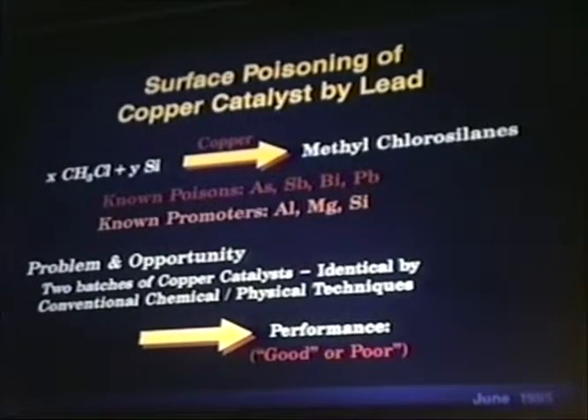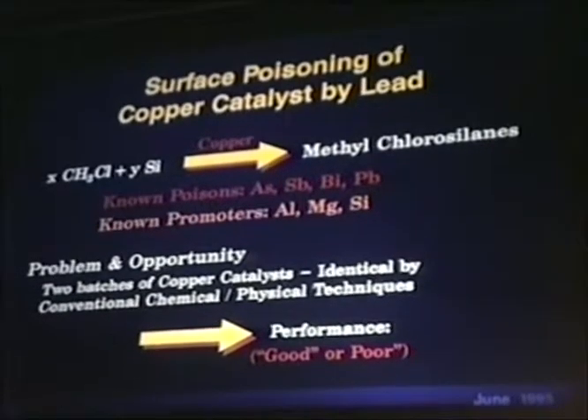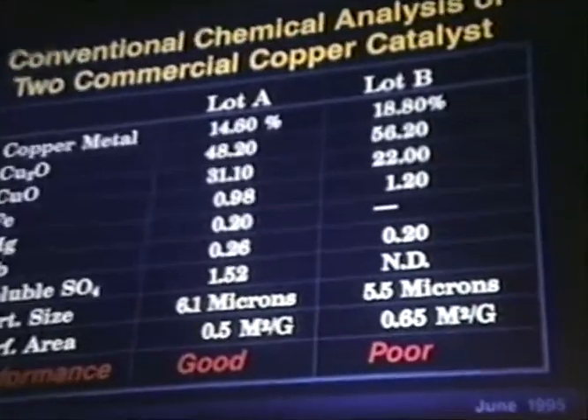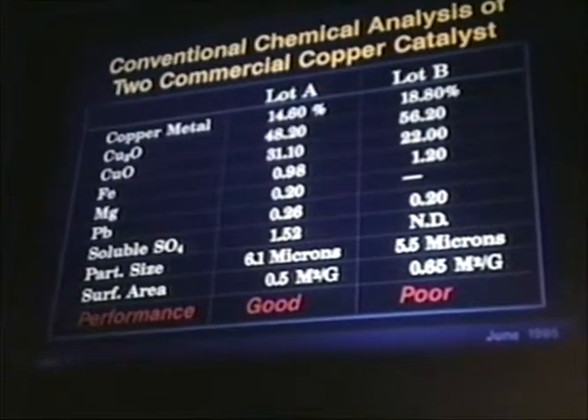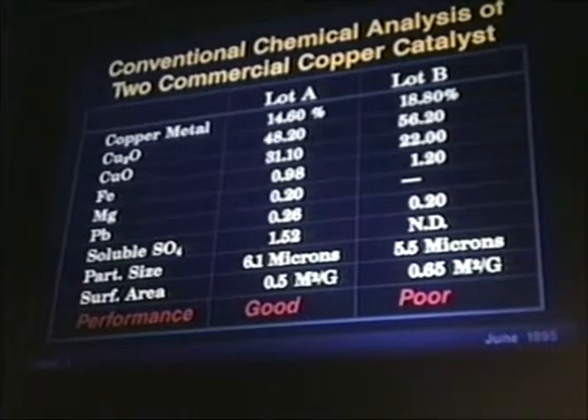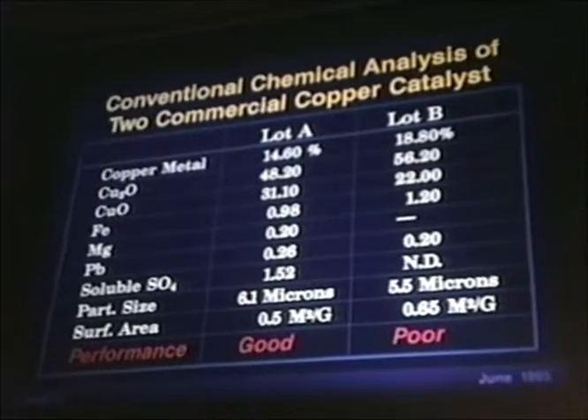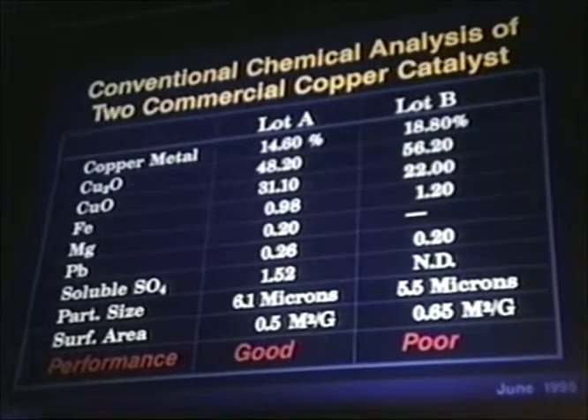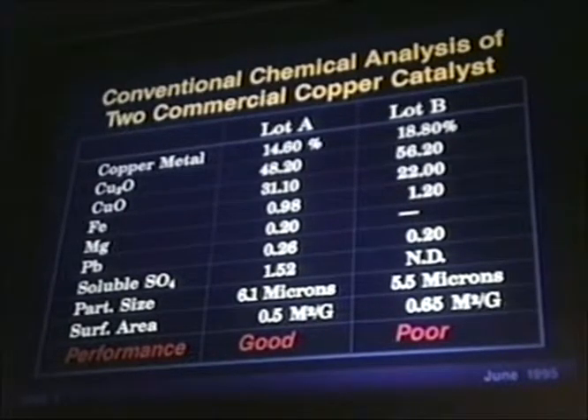It's a commercial process, and we have had in the early days of surface science a real problem, and that is some batches of catalysts will be made and we could not distinguish the performance of the good and the poor catalyst systems. But it was also an opportunity. Doing the conventional analysis, which is covered here, you can look at all the detailed analysis of both the oxidation state, cuprous, cuprate, and all the other impurities, and the soluble sulfate particle size, if anything, was in the other direction, yet the lot B was very poor in performance.